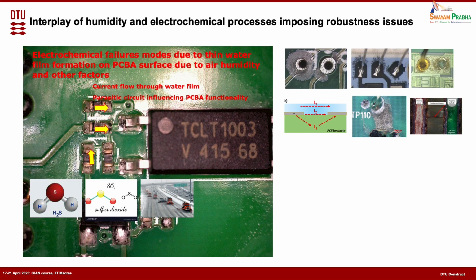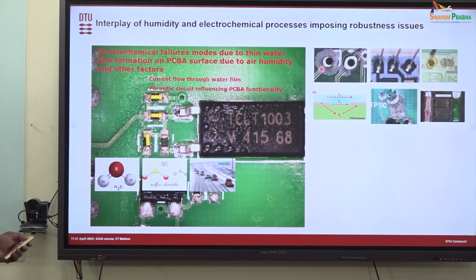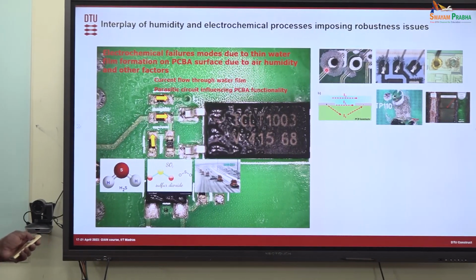That means that corrosion has occurred on a copper part, and then the corrosion product is spreading. That's the reason it is called creeping. So it's creeping across the surface. More of a cosmetic issue. It may not create a failure immediately.